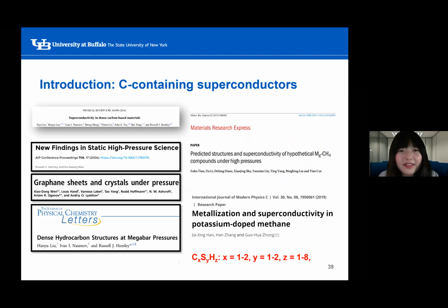Another factor is that there are interesting carbon-containing superconductors. Dense carbides have been predicted to be superconducting, and are very stable due to their sp3 framework. Hydrocarbons were studied and found to be stable at high pressures. Also, the ternary systems made by doping methane with either magnesium or potassium were found to be superconducting. Combining these factors with the fact that trihydrogen sulfide was predicted to be a high-Tc superconductor, we were encouraged to carry out our study on the C-S-H systems with the stoichiometries shown here.